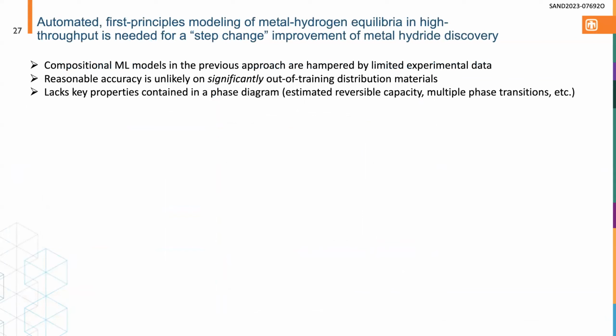So that's one way to look at this problem. But you might be wondering, well, that's a pretty simplistic prediction to take all the information contained in the PCT curve and just simplify it down to scalar values. And you're right, there's a lot of issues with that. So compositional models, first of all, are hampered by limited experimental data. And the bigger issue is that accuracy on significantly out of training distribution materials is unlikely. And we're lacking key properties of the phase diagram, like potentially the reversible capacity, the width of the plateau, as well as whether other secondary effects happen that we're not so excited about.